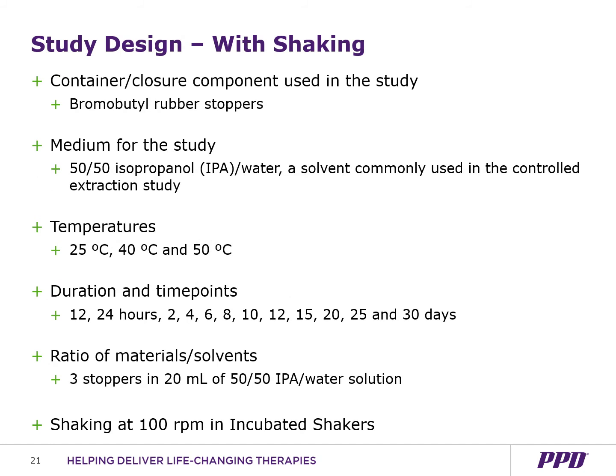We used the same overall study design where we used the same rubber stoppers with the solvent medium of 50/50 IPA water. We used the extraction temperatures of 25, 40, and 50 C, so we removed the 5 C and 60 C. We abbreviated the study and added some additional early time points ranging from 2 hours to 30 days. We used the same 3 stoppers in 20 mL of solvent for extraction.